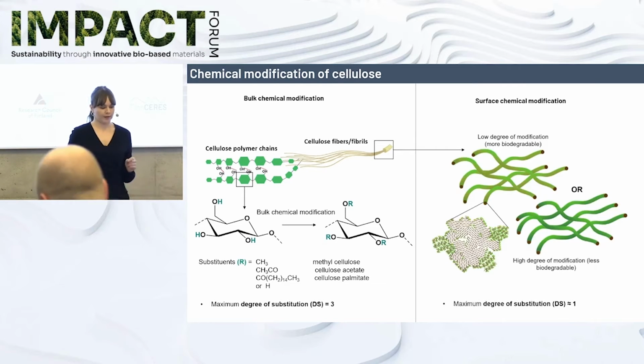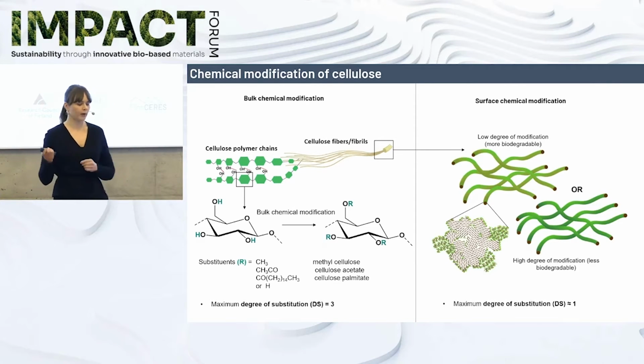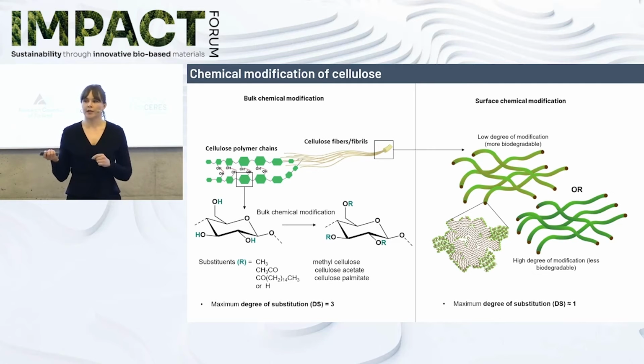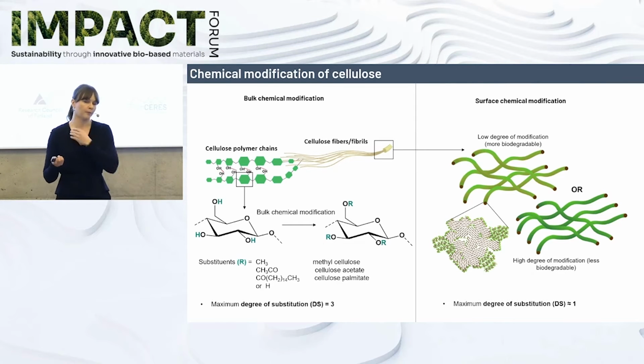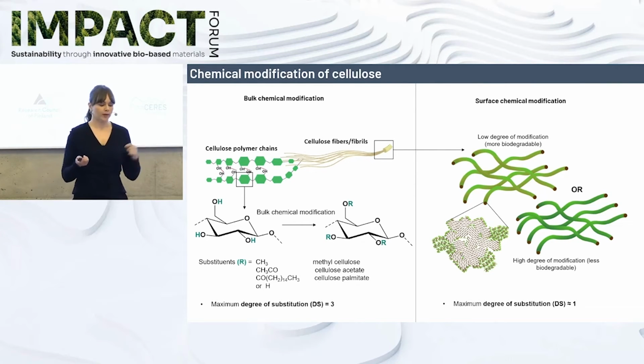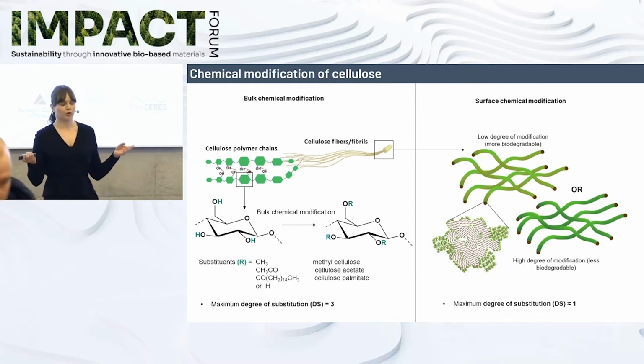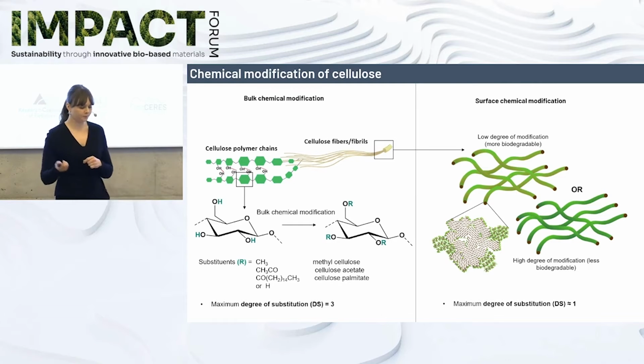And then to the surface chemical modification. There we do not dissolve the cellulose fibers, but we actually do the chemical modification only on the surface of the fibers or fibrils, so that the inner part of the fibers remains unmodified. So here the maximum degree of modification is only approximately 1, because if we go above that, it will start dissolving the cellulose fibers. So this already is a way to control the biodegradability.